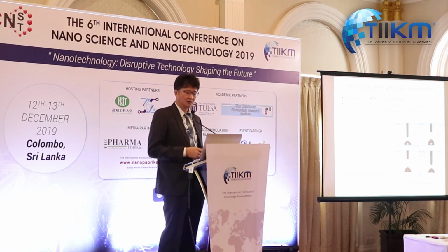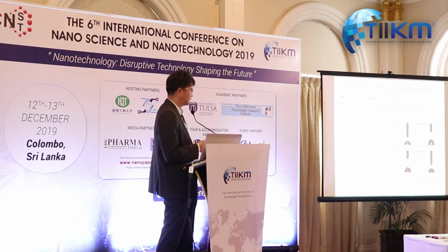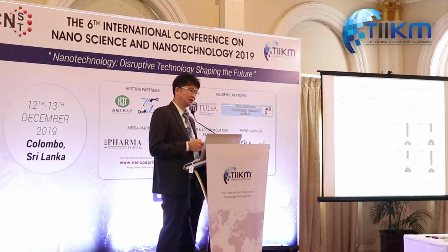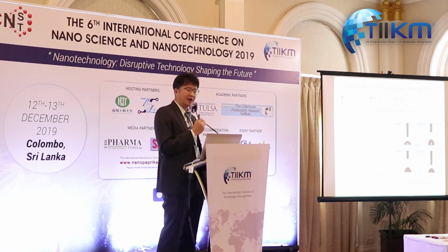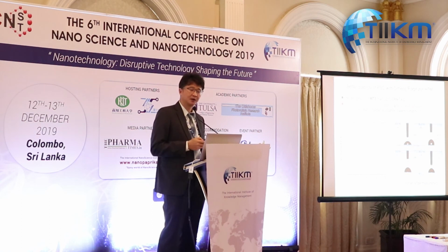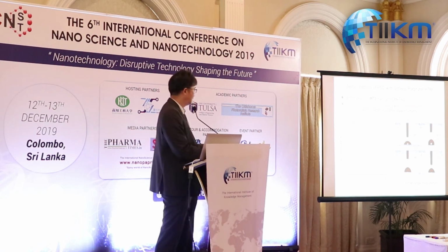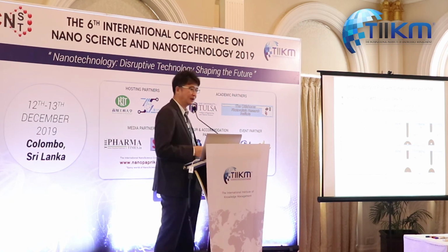So we also did the contact angle. We studied the hydrophobic property of the hole transporting materials using the contact angle method. The contact angles between the hole transporting material and water are shown here. For spiro it is 65 degrees, and Y2 81 degrees, YR3 90 degrees, and WT3 103 degrees.